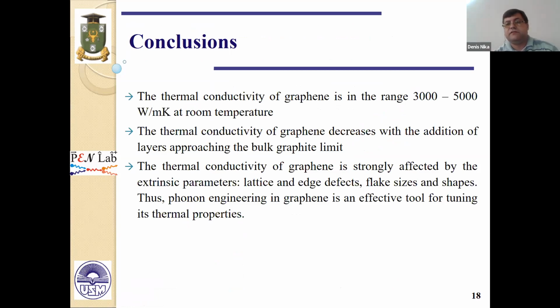And the main conclusion of my talk you can see in the slide. Thermal conductivity of single layer graphene is very high, in the range between 3000 and 5000 watt per meter Kelvin at room temperature. The thermal conductivity strongly depends not only on temperature but also on extrinsic parameters of flakes: on defects of the crystal lattice, on edge roughness, on flake sizes. Therefore graphene gives us very interesting opportunities for tuning thermal properties by changing extrinsic parameters. Thank you very much for your attention.